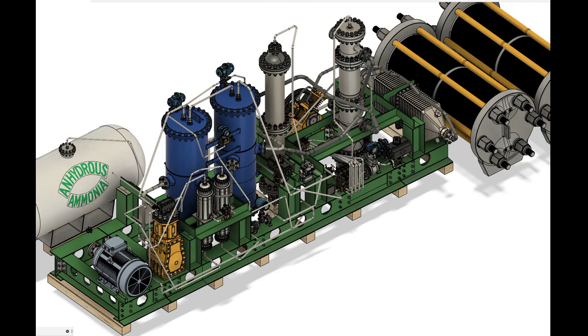There is approximately 19 kilograms of natural gas in 1,000 cubic feet or a million BTU. The price of producing hydrogen from natural gas is only $1 to $1.50 per kilogram. Around 3 kilograms of methane is required to produce 1 kilogram of hydrogen using steam methane reforming. Therefore, the price of ammonia should be still below $500 per ton.